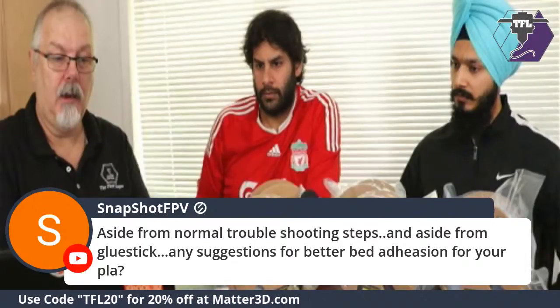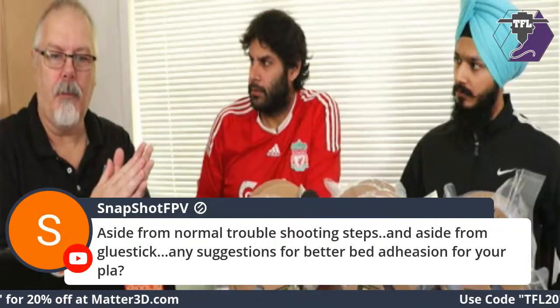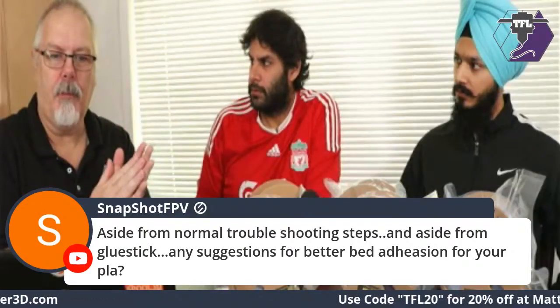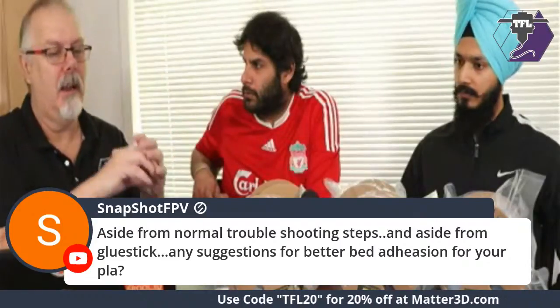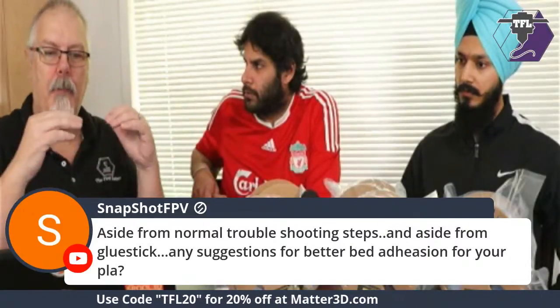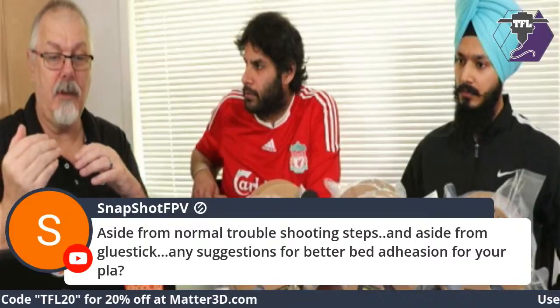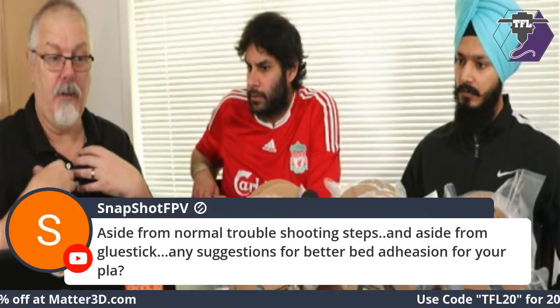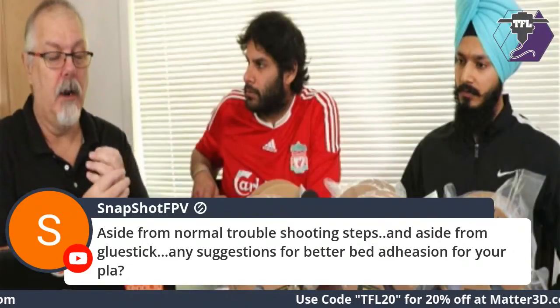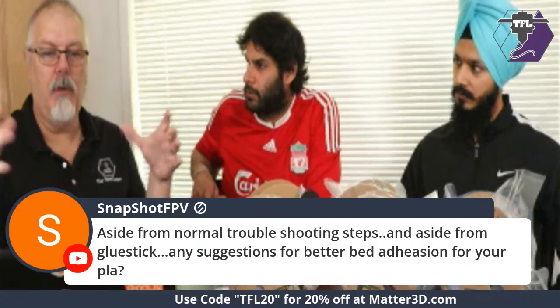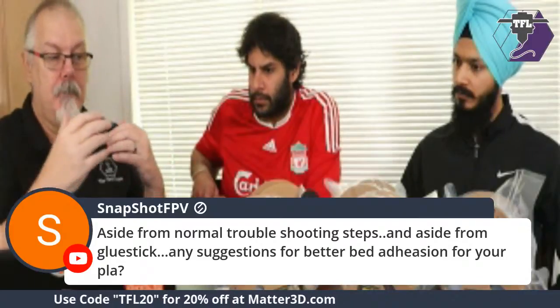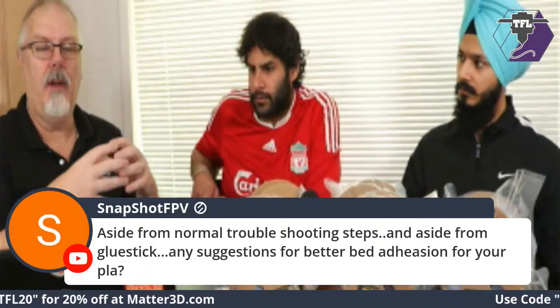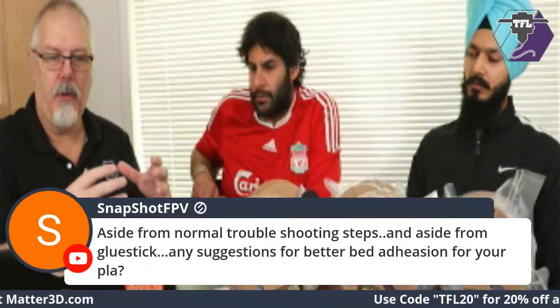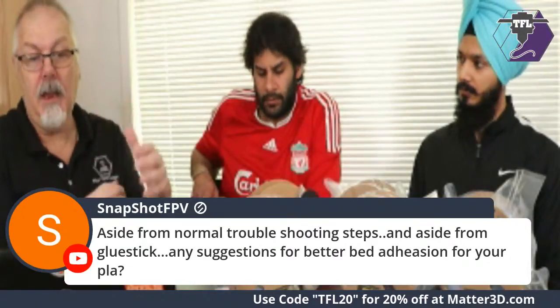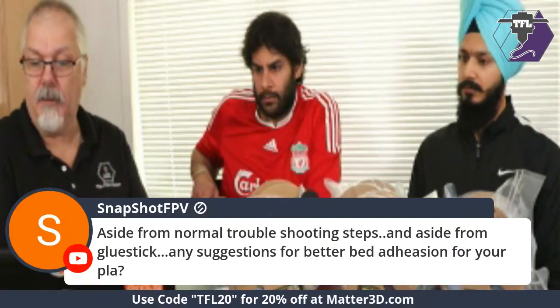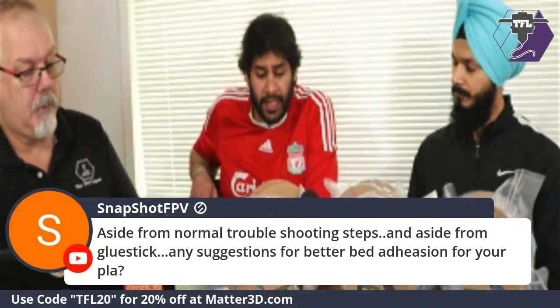Here's the thing that a lot of people have a problem with, and that's curling or shrinking of the material. This material doesn't shrink like typical normal materials do. So if you've got that bed a little bit too hot, if you're up in the 70-degree area, I've printed it at 70 degrees, never had a warping issue whatsoever. How you get warping is you've got too much cold air around your printer. This material, because it's made with a high quality raw resin, it doesn't shrink, and I can attest to that. So yeah. And well, go ahead.